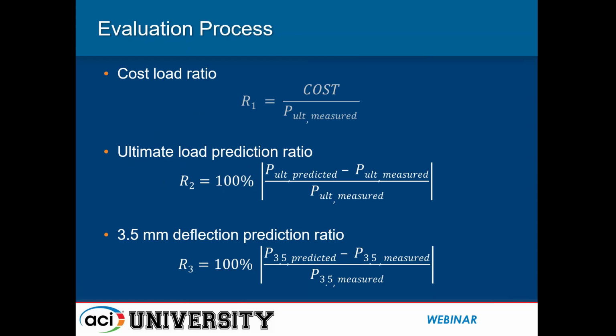Now, for the evaluation and results, the cost to load ratio is calculated as a value R sub 1. That is equal to the cost divided by the ultimate load that is measured. The ultimate load prediction ratio, R sub 2, is a percentage calculated by subtracting the ultimate measured value from that you predicted and dividing that quantity by the ultimate measured value. Similarly, the 3.5 millimeter deflection prediction ratio is calculated by subtracting the measured value from the value you predicted and dividing by the measured value and placing those in percent format.